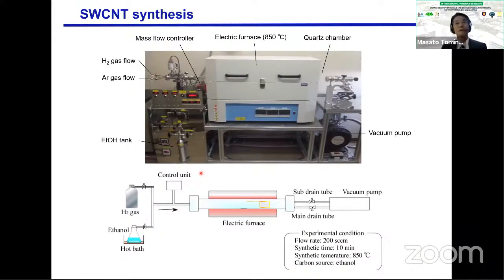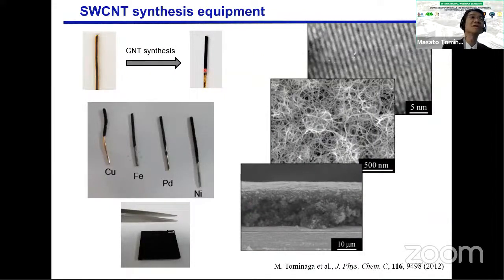So we synthesize carbon nanotubes directly on the electrode surface to remove such contamination and such problems. We use this CVD equipment, an electric furnace. A closed chamber is set in this furnace, and we use ethanol as a carbon source, and we control the ethanol gas by using a mass flow controller. Then the electrode modified with the catalyst is set in the closed chamber, and then we obtain carbon nanotubes. This is before carbon nanotube synthesis. This is after. The surface changed to black like this one.